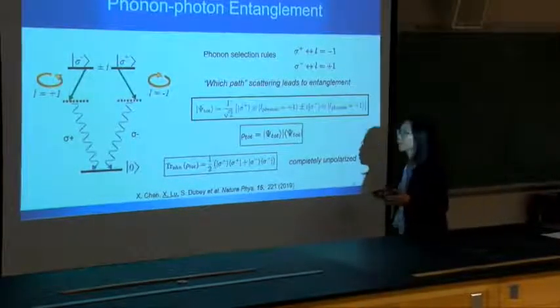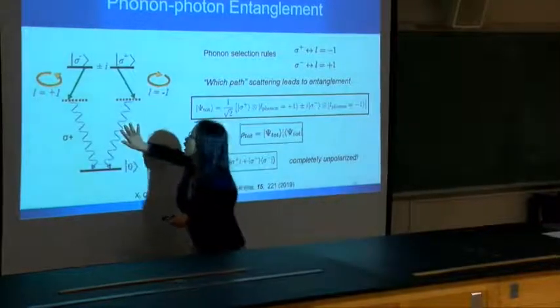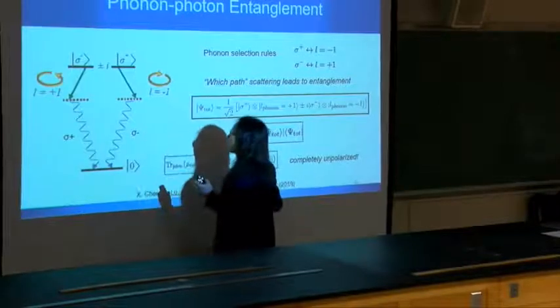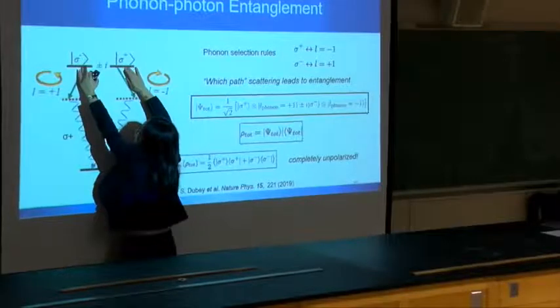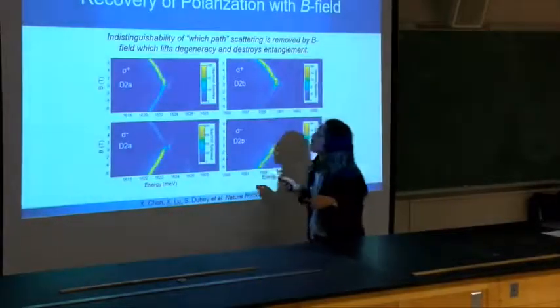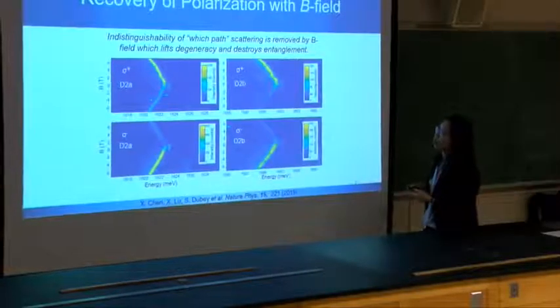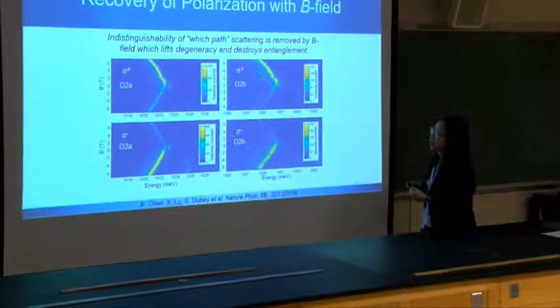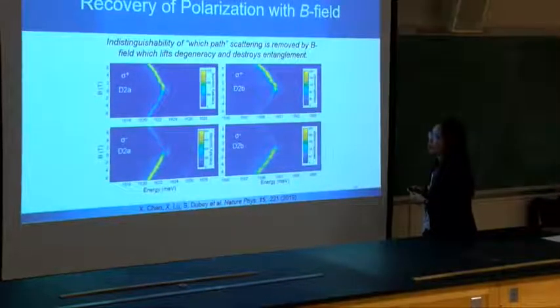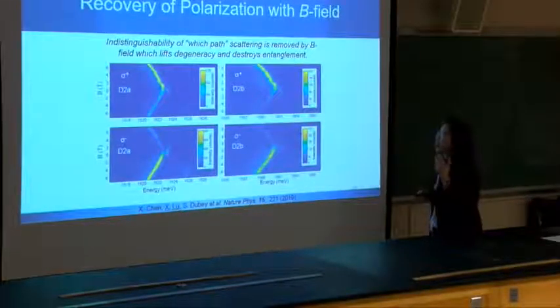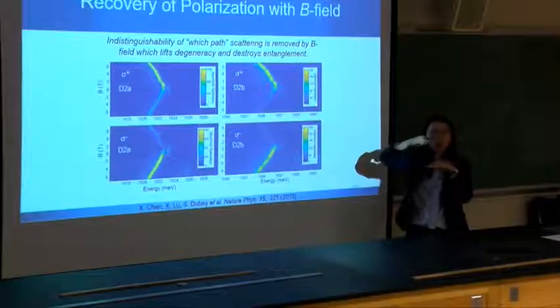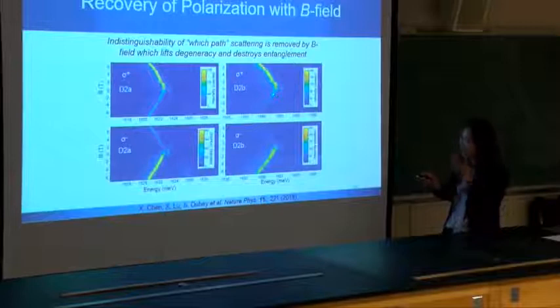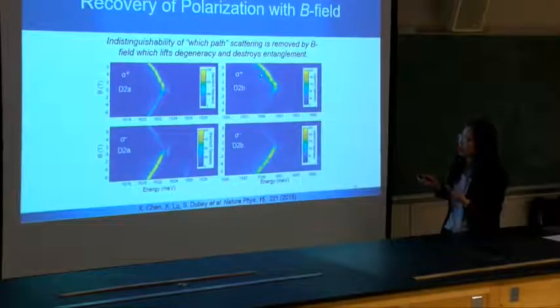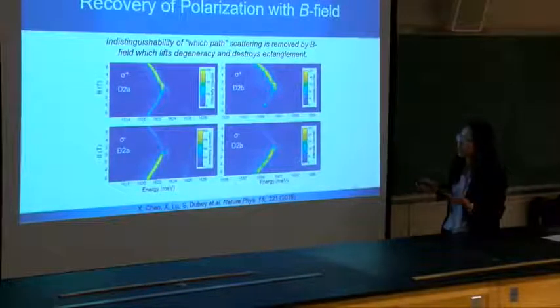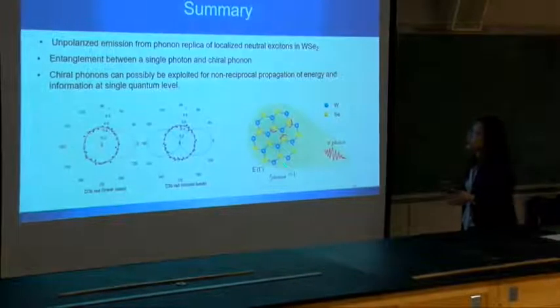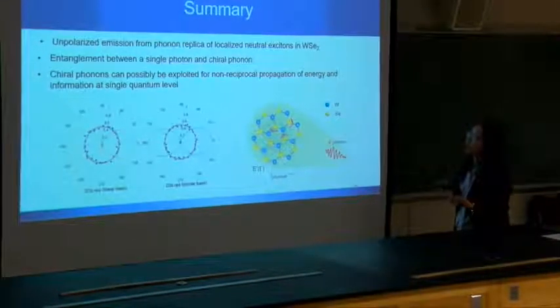But in the meantime, we are also thinking that these two paths are indistinguishable. If we somehow break this indistinguishability, for example, let's say we apply a magnetic field and these two are not degenerate anymore, what will happen? So that's why we are applying a magnetic field and doing this measurement. And what we found is that when we apply a magnetic field, the unpolarized phonon replica gets circularly polarized, which means that the degeneracy is broken and the entanglement is not there. Consequently, the polarization of the phonon replica gets recovered. So that's the unpolarized emission from this entanglement.